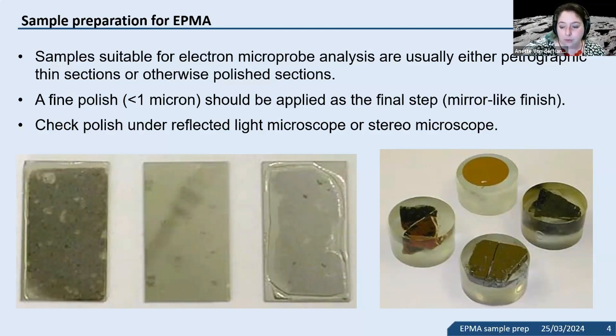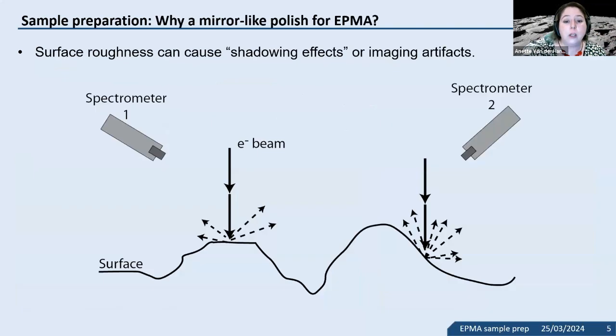If they are not polished well enough, or not polished well enough throughout, there can be all kinds of problems. So why do we care? Why do we need that? Even if you do EDS on an SEM, there are certain things that apply to everything. Just because the EDS tends to normalize to 100 doesn't mean that you're getting accurate and good data. So the first thing is that surface roughness can cause shadowing effects or imaging artifacts.